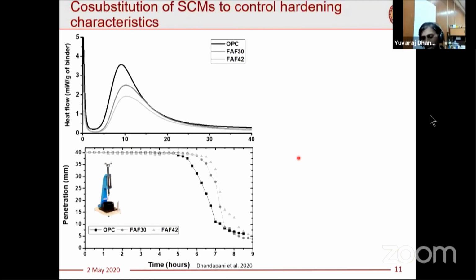The other aspect which I want to talk about is the impact of this hydration curve in terms of some characteristics. So you can see with increasing fly ash, the curve shifts to the right and the heat flow is less. So when you do a simple VICAT test, the penetration resistance starts shifting this side, which means a high volume fly ash binder has delayed setting characteristics compared to a PC system.